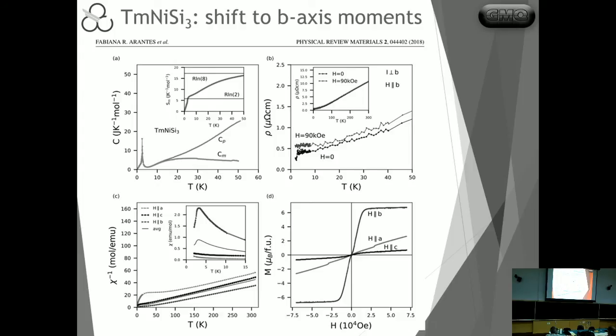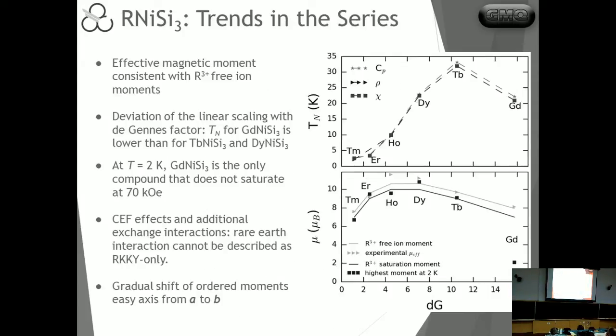Moving on to thulium, then we start seeing a very strong easy alignment along the B-axis with very low response from the other directions. And then, as we had already seen previously in terbium, which is the last one, it's just fully B-axis with no response from anywhere else in this case. So this is what we could follow in terms of the series, how it evolves as we replace the magnetism.